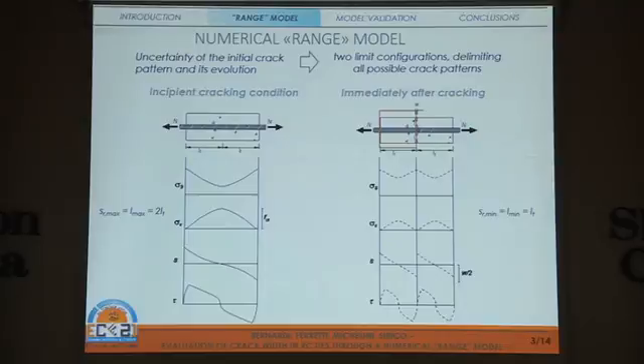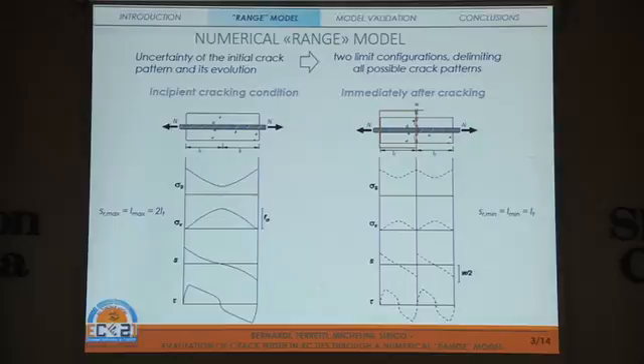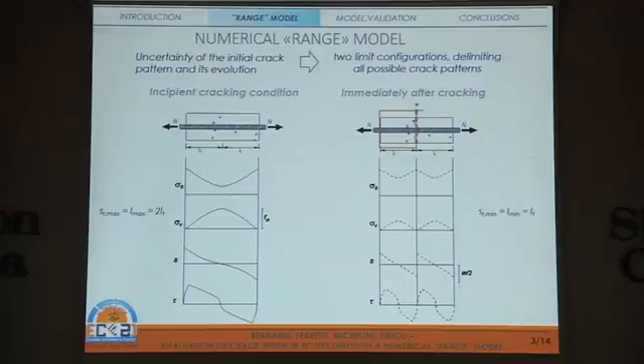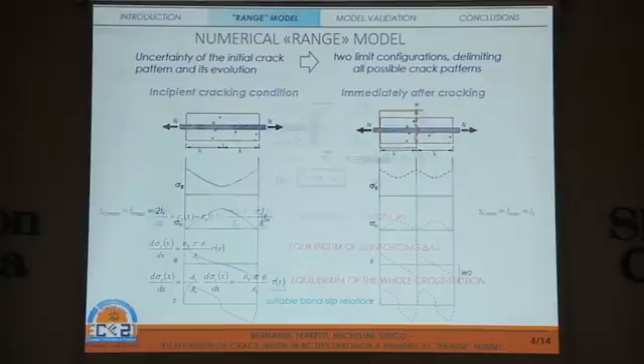These two limit configurations are the incipient cracking condition and the condition which takes place immediately after cracking. In the first case, the attention is focused on a tension tie block with length equal to two times the transmission length — the length over which slip occurs between steel and concrete — where the stress in concrete equals the maximum tensile strength of the material at the mid-block. Immediately after cracking, a crack forms exactly in the middle of the previous block, creating two blocks each of length equal to the transmission length, which is also equal to the minimum crack spacing. Crack width is defined as twice the slip that occurs at the block ends.